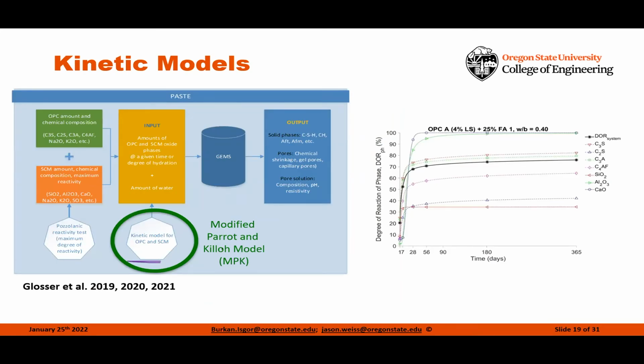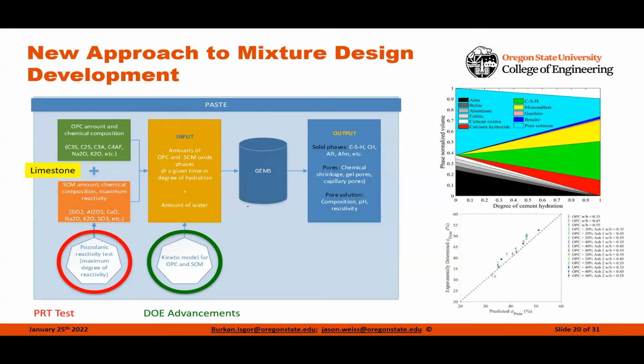And in doing this, we've modified the classic Parrot and Kilo model that's been used for cements. And we've added several of these other systems in to get the reaction kinetics for a lot of the SCMs that we're looking at. We can now run this through the thermodynamic modeling, and we can predict the phases. So we can predict how much CSH, calcium hydroxide, and a lot of the other phases there are. We can predict the chemical shrinkage, the gel porosity, the capillary porosity. All of these things can be predicted.